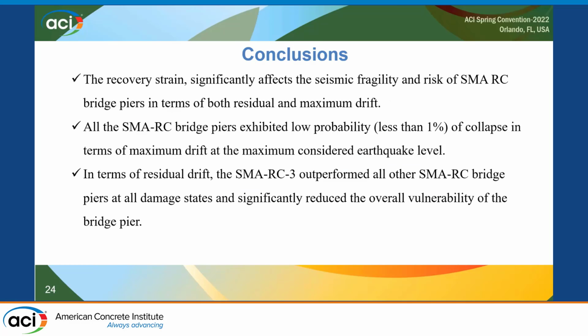So to conclude, we can say that the impact of different components on the probabilistic seismic design model and the fragility of the bridges were evaluated in this study, from which we can draw the following conclusions. Number 1, the recovery strain significantly affects the seismic fragility and risk of the SMA-RC bridge piers in terms of both residual and maximum drift. And all the SMA-RC bridge piers exhibited very low probability of collapse in terms of maximum drift. And if we consider the residual drift, SMA-RC-3 outperformed all the other bridge piers at all damage states.